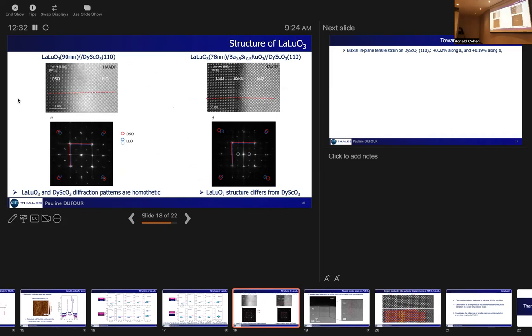This is further confirmed by STM measurements, where when you have LLO directly grown on DSO, you see that you have a homothetic relation between the diffraction spots of the DSO and the LLO, suggesting indeed that we have the same symmetry. Whereas as soon as you introduce even a few unit cells of barium strontium ruthenate, the symmetry of LLO will diverge from that of DSO, which confirms this change of orientations.